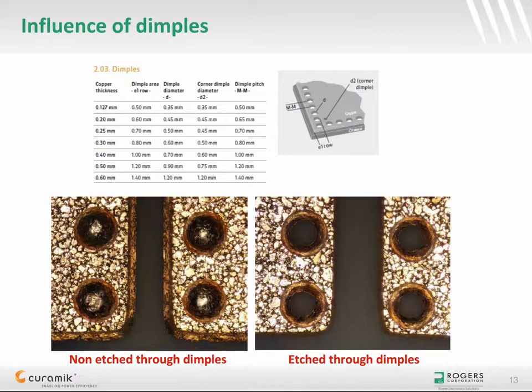Luckily, there are other options to increase the reliability by design and without adding significant cost to the solution. As a first example, we will speak about dimples here. Basically, dimples are holes in copper metallization. Curamik has developed a proprietary dimple design for the purpose of thermal stress relief. The objective of such dimple design is to reduce the copper thickness on the edge of the copper pad and hence increase the lifetime by reduction of the thermomechanical stress in these areas.